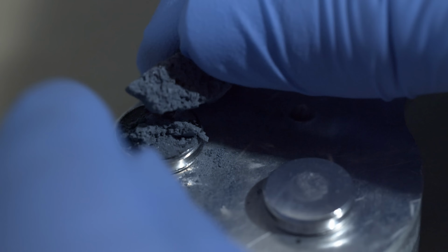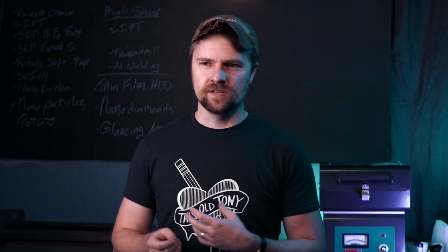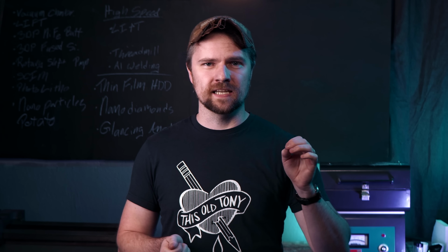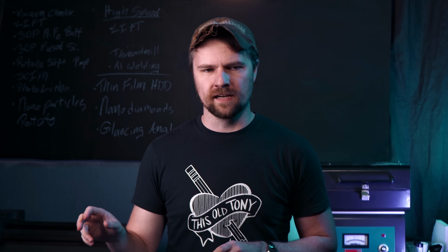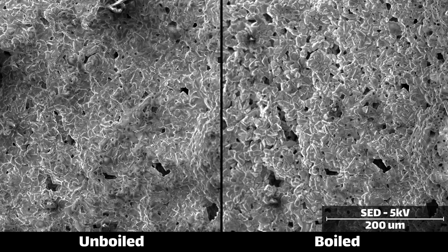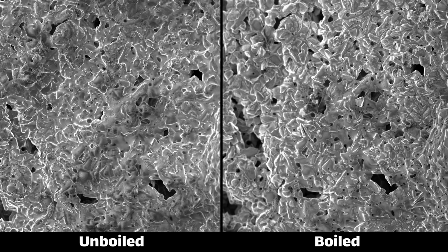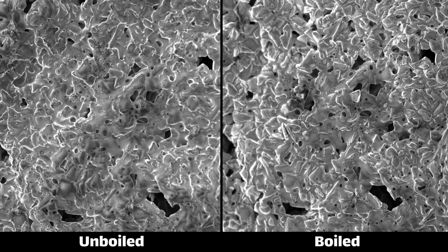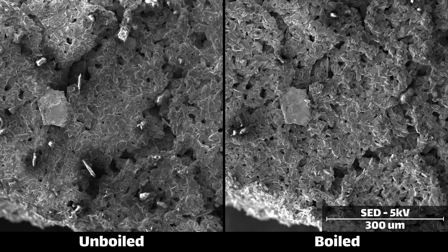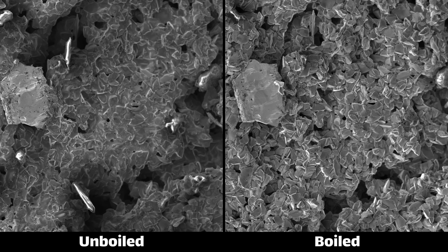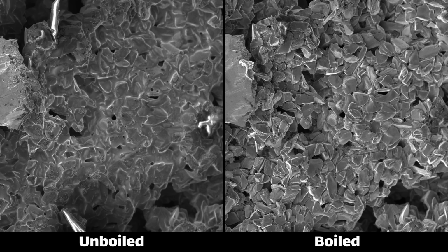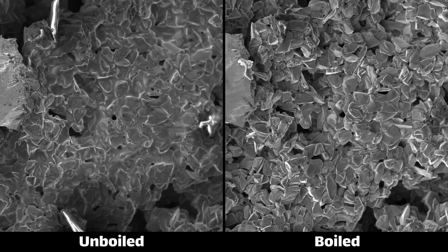So I repeated it with different samples, and I didn't have quite as dramatic of an effect as that one. And so the samples held together, and I was able to get matching images before and after boiling, but you can see morphology changes between the two in some places. So in some places, nothing changes. In this image, for example, it looks reasonably the same between the two. But in other locations, you can see a pretty distinct change where the individual grains of silicon carbide become much more pronounced. That kind of liquid network in between has gone away to some degree.